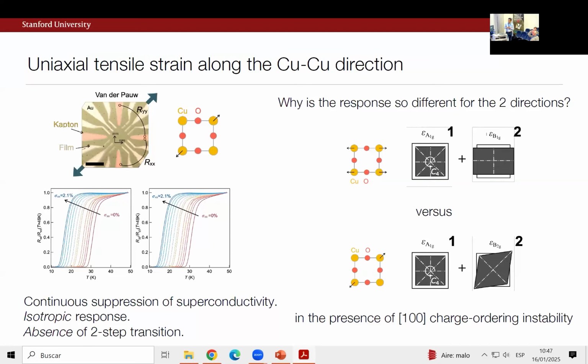and in particular in the context of this charge ordering instability. That is to say, let me just put my own interpretive words, if we have a situation where we have a stripe phase and superconductivity and they're doing something like this together, does strain either stabilize or destabilize that stripe instability? So we think this might be what's going on.